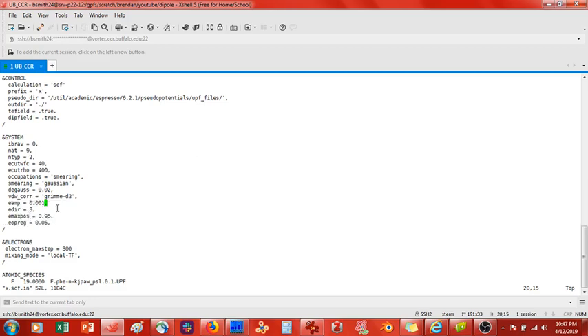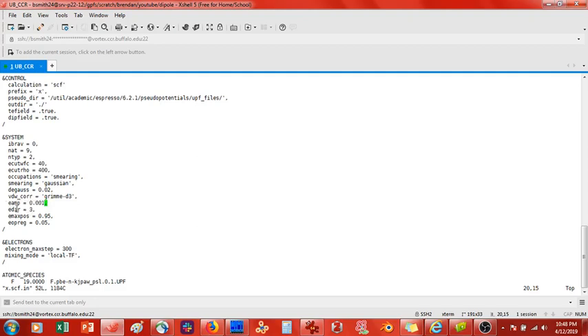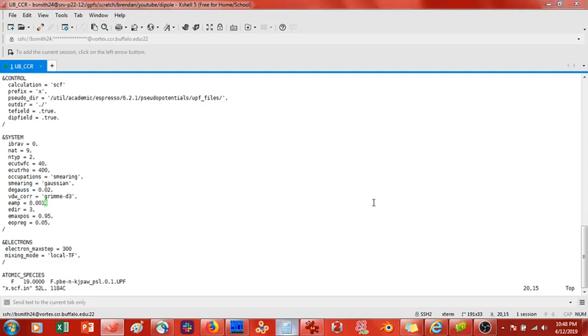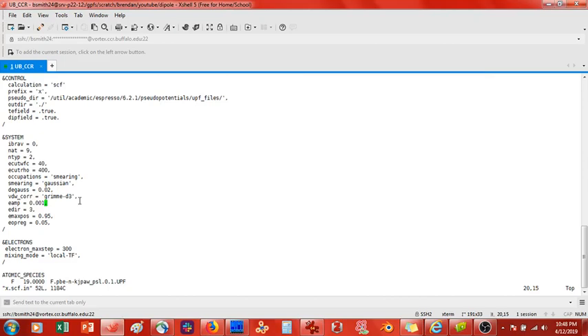And so in the sawtooth potential I drew last video, there was some slope associated with the sawtooth potential as it moved through your unit cell. That's what this e-amplitude is. And right now I have it set at the default value, and one thing I wanted to mention to you all is that this value is in Hartree, so any change in this is pretty significant. That's why we have it so small. So for example, one Hartree is over 27 electron volts, so this is like 0.02 electron volts. Let me see if my math is correct. So it's 27.2 times 0.001. Yeah, this is how many electron volts is our slope on the sawtooth potential.